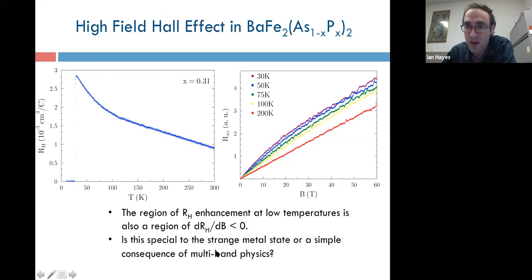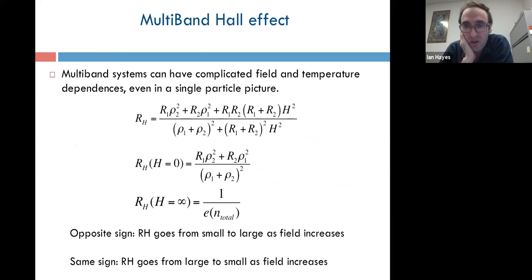So I just want to say a few words now about what one expects for a system like barium-122 based on the simplest multi-band model. So if you have multiple bands, the simplest thing to do is add the conductivities in parallel, and it's an Ashcroft-Mermin level problem to just put them together. And there are just two limits I'd like to highlight for you. One is the H equals 0 limit. In the H equals 0 limit, you get a Hall coefficient that's just the weighted average of the Hall coefficients on the different surfaces, weighted by the conductivities on their respective surfaces. And then there's the high field limit, in which you get an effective RH that is determined by the total carrier number, electrons minus holes. And so generically, in a system like barium-122 that has electrons and holes in approximately equal numbers, you'll start from a fairly small RH, because these two terms will nearly cancel.